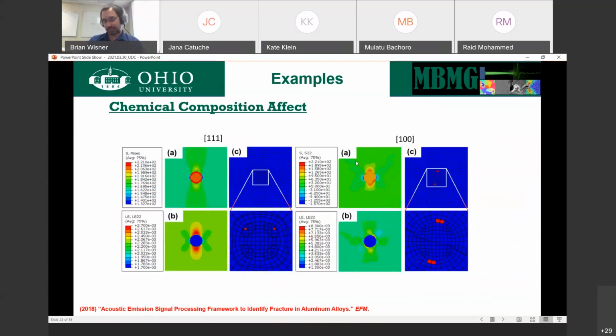If we also take into account not just the difference in properties of the particles, but the crystal orientation. So in this case, we're changing the aluminum to be 111 orientation versus 100 orientation, hard versus soft. You'll notice that the concentration of these red dots indicate where fracture is going to happen, at least where we think it's going to happen. In this case, in the hard orientation, we expect the fracture to actually occur in the particle itself. So the particle, the reinforcement, is going to fracture. In the case of the soft grain, actually the aluminum or the bonding between the aluminum and the particle should be what fails. So we have two mechanisms. If we want to know that these two mechanisms can change the behavior, and these are what's a concern, can we detect them? Can we detect one? Ideally both, but can we detect at least one?